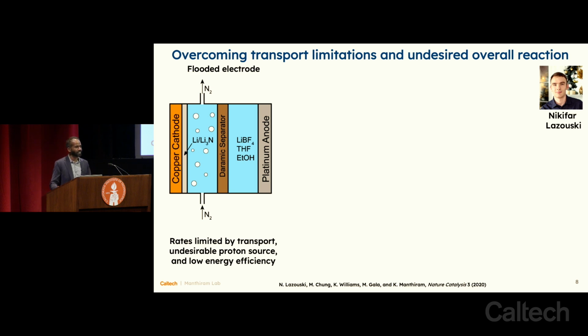As we started working on this chemistry, the first thing that we recognized was that we needed to make a more robust reactor architecture. So we went from having two tiny wires dangling in a beaker to something that was more scalable. Here we have a copper foil cathode on the left side and a platinum foil anode on the right side. We have a separator, which just helps to keep the two compartments apart from each other. We have an electrolyte that is lithium tetrafluoroborate in tetrahydrofuran, still with ethanol as the proton donor. In this cell, we are bubbling through nitrogen gas. That nitrogen gas is reacting with lithium metal that's deposited on the surface of the copper cathode. These are really small amounts of lithium in inventory, so the safety hazard is really eliminated.